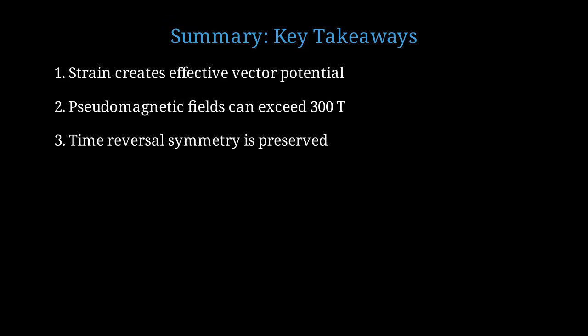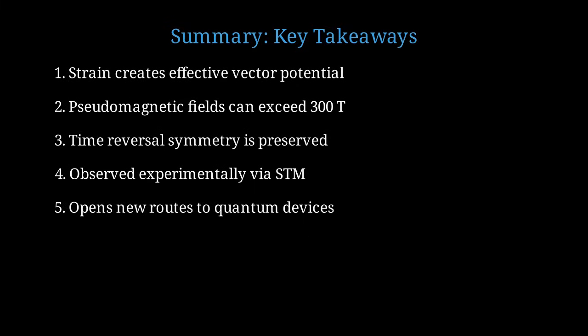Let me summarize the key points from this lecture. First, mechanical strain in graphene creates an effective vector potential that acts like a magnetic field on electrons. Second, these pseudomagnetic fields can reach strengths exceeding 300 Tesla, far beyond laboratory magnets. Third, unlike real magnetic fields, pseudomagnetic fields preserve time reversal symmetry because they're valley-dependent. Fourth, these effects have been directly observed using scanning tunneling microscopy in graphene nanobubbles. And fifth, this opens entirely new routes to creating quantum devices and studying high-field physics without actual magnets.